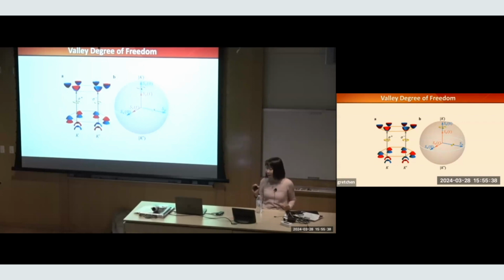Valley itself just means a minimum or maximum in the band structure. Every material has valleys, but typically you cannot controllably occupy or confine the response to one valley. This material has the unique property: you can actually choose to populate one valley or the other valley, or you have light emission that is sigma plus that comes from one valley and sigma minus from the other valley. So it almost gives you another binary degree of freedom to encode information. People call this valleytronics, which is based on this idea. The valley index is binary and has different properties that allow you to encode information.